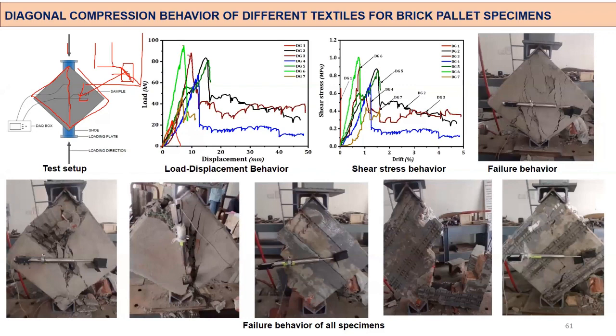Now it comes to the textile case. It comes down, as I mentioned earlier, with reference to the crack opening and the textile rupture. It keeps on going like this. In the textile behavior, we can see a lot of cracks, which shows that this particular wall sample is expanding in this direction, but the provided textile holds the whole wall together and resists the applied force by creating a wonderful interaction between the surface and the textile layer. After the testing, we open it up to see what happened internally, as you can see here.